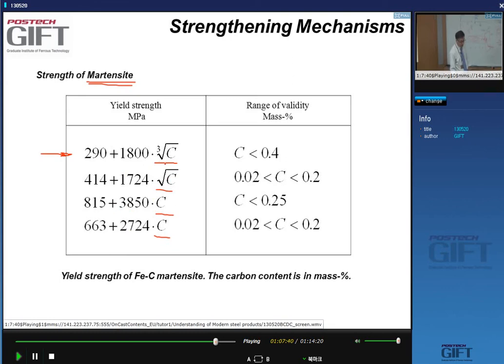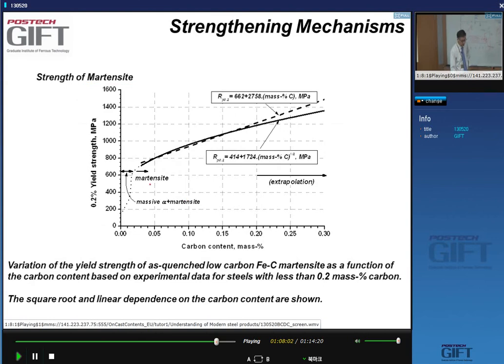But the interesting thing is that you can see that also here, it's unclear to the researchers what the exponent is of the carbon content that you should use to express the relation between carbon content and solid solution strengthening. In fact, you see the reason here: you have two of these relations, the yield strength as a function of carbon content. One has the yield strength being proportional to the carbon content, and the other has the yield strength being proportional to the square root of the carbon content.